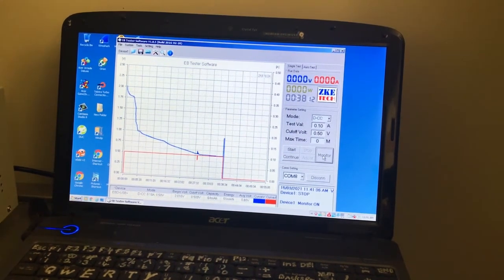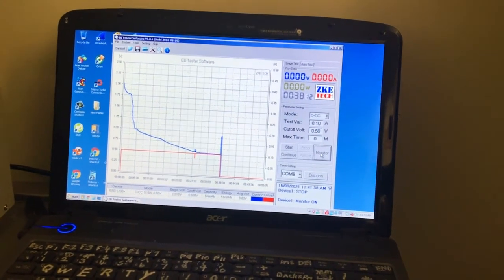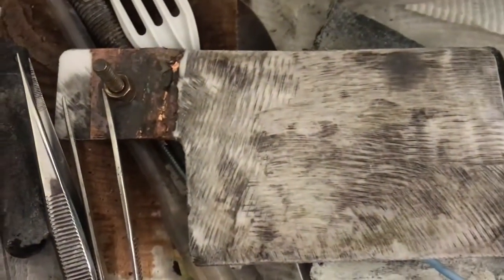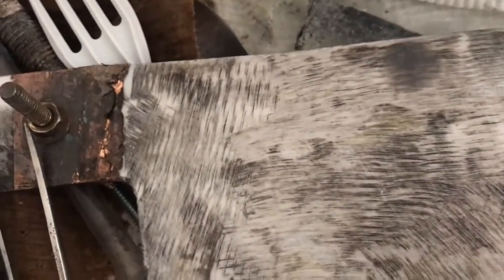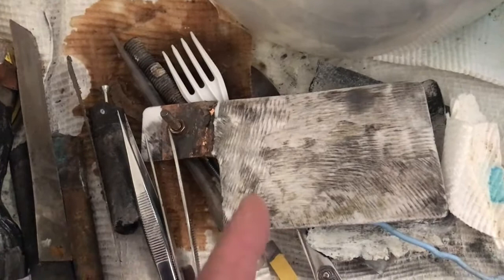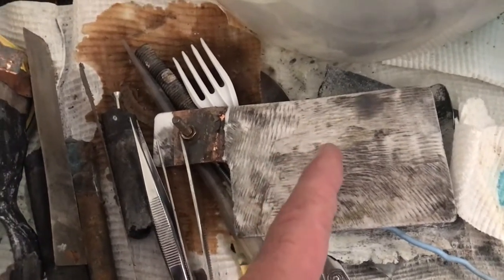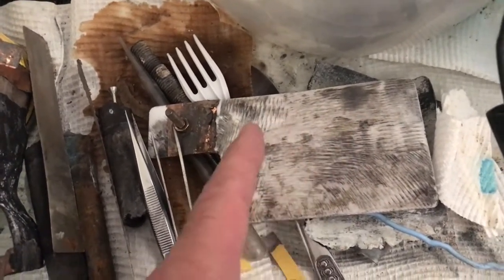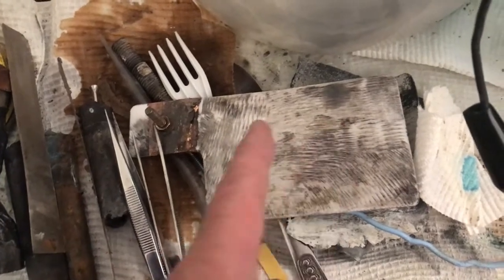Okay, cell fell over, only 38 minutes. I know the reason. I did an autopsy on the thing. That's the plate. Either I didn't coat it thick enough, but there were two issues. The binder, the stuff was down at the bottom, so it washed off, and I'm not sure if I ripped it or there was a slight rip through the copper and the nickel on the cell.